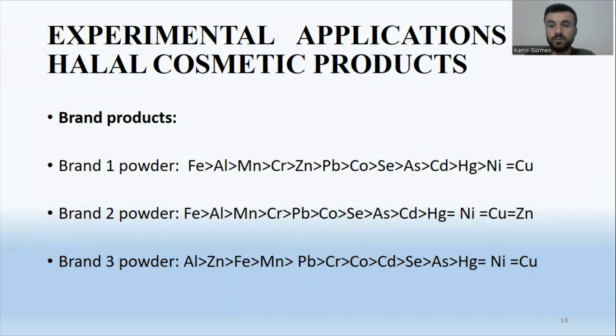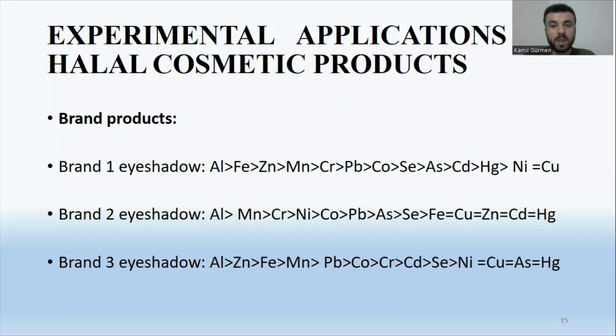In the results obtained for the powder in the analysis made for all brands, it was shown that iron, aluminum, manganese, and zinc heavy metals were found at high rates. Occurrence of brand 1 powder: nickel and copper. Brand 2 powder: mercury, nickel, copper, and zinc. Brand 3 powder: mercury, nickel, and copper were not found elements.